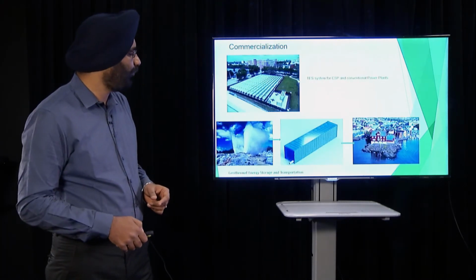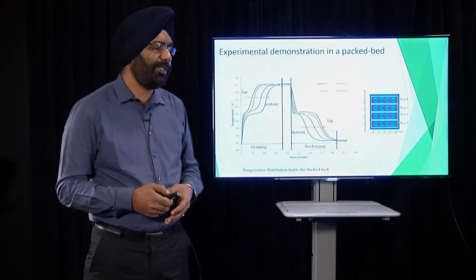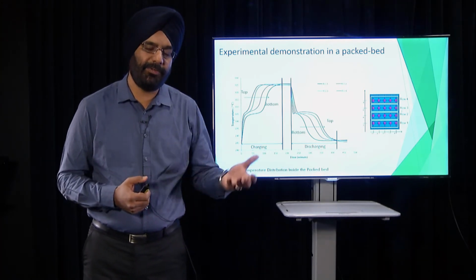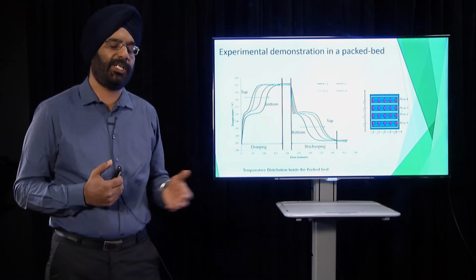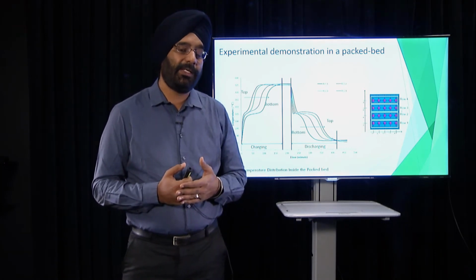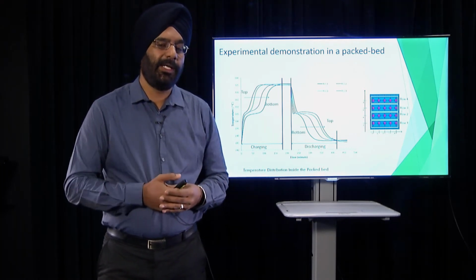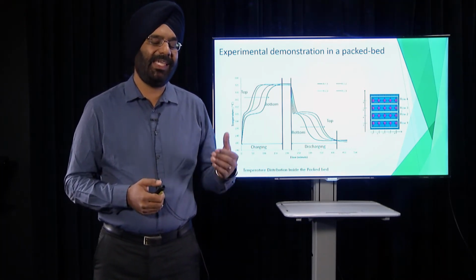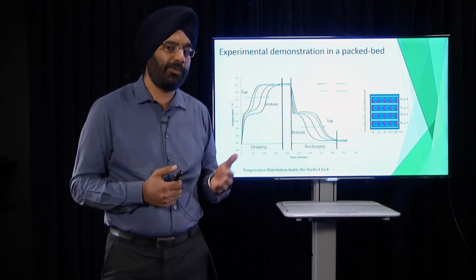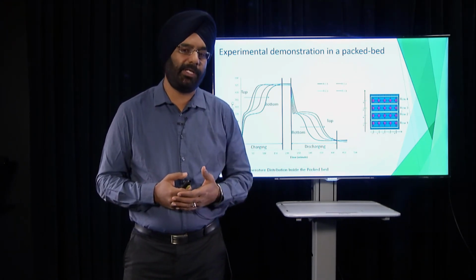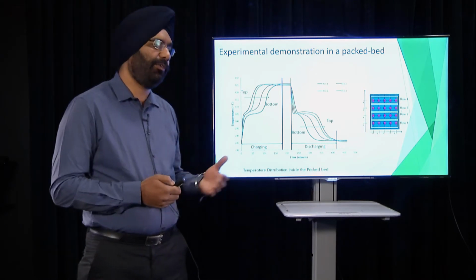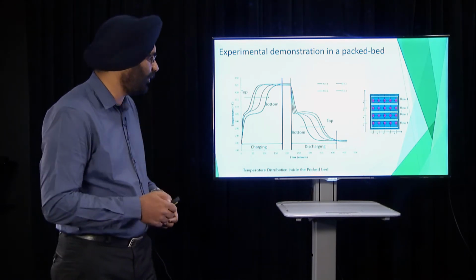So based upon these calculations, we could see the performance of the capsules, we could see the charging and discharging time of the system, and most importantly, we could also determine the efficiency of the system, which is close to 90%, a very, very good efficiency as far as an energy storage system is concerned.